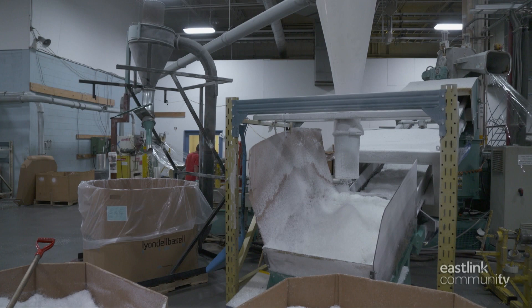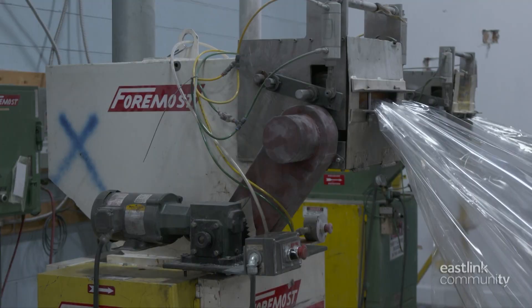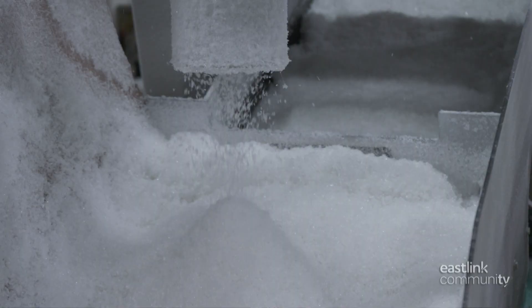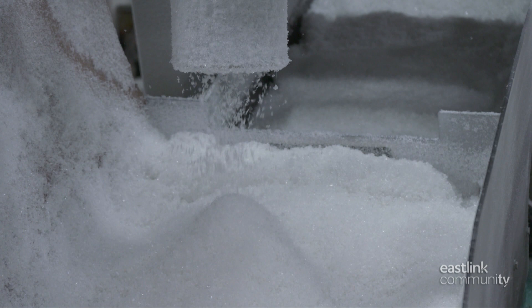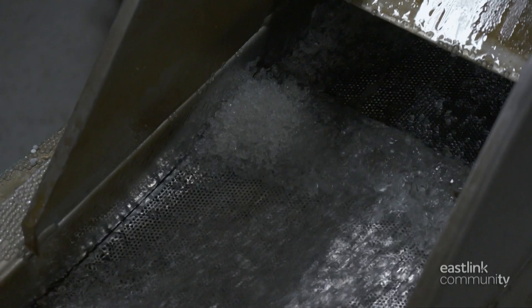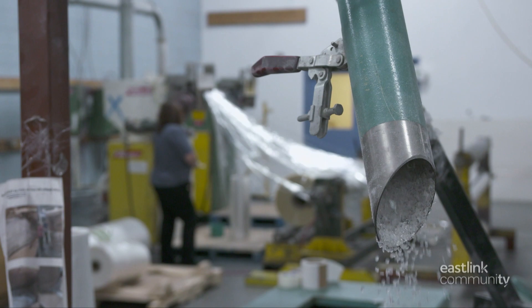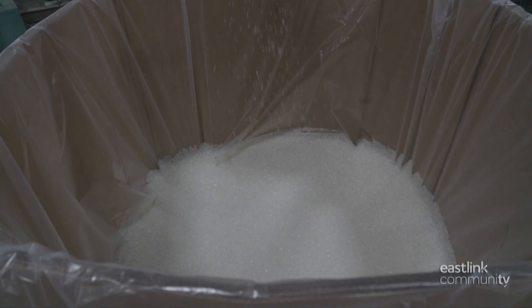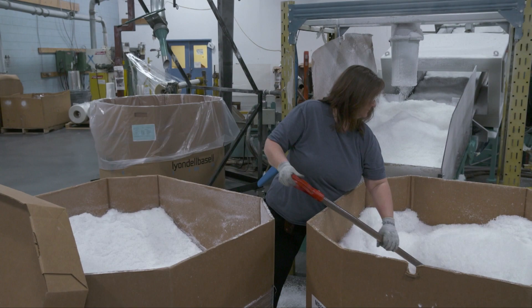No plastic film is wasted in the plant. Any extra film from trimming, start-up rolls, or from any production problems is recycled right on-site using a reverse system. The unused film is loaded onto the line and fed into grinders, where it's ground into what they call fluff. The fluff is sucked up through pipes to a belt that feeds it into a small extruder, where it's melted and pushed through a die where a rotary blade cuts it into pellets — referred to as reprocessed plastic. It's cooled in water, then moves along a belt to be dried and blown into a storage bin, ready to be used in production. The workers manage the different types of film in the recycling line to ensure the pellets will work with recipes for the main production line.